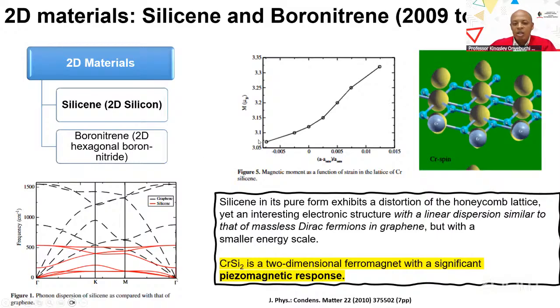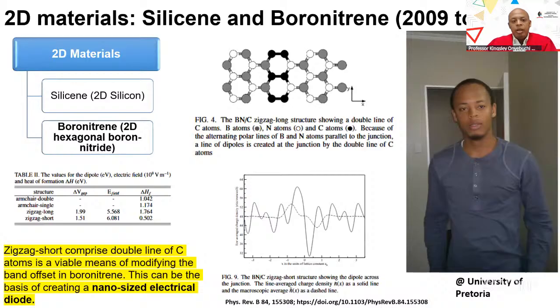So you can see as you apply pressure in this material, so this is the pressure we applied and this axis is strain, you can see that the net magnetization changes. It tells you that you can actually use this for systems that require piezo-magnetism. So this provided a basis for us to understand this kind of system and possibly get an application from this. The next part is, this is in 2011 when I joined the University of Pretoria.